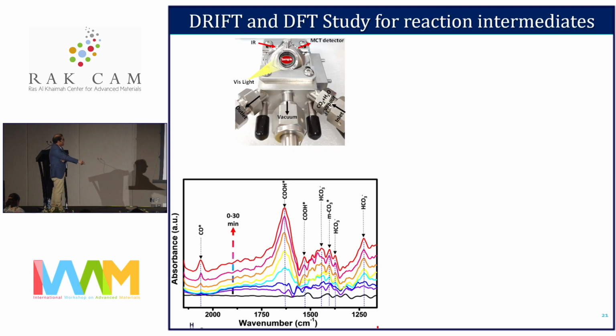To further understand this, we performed an operando study - this is the DRIFT study. After 30 minutes of irradiation, first you have the background without CO2, only the catalyst. Then, with the presence of CO2, you irradiate the light - this is the Mantis chamber. Over time, you first get the carbonate, bicarbonate, and monodentate carbonate. Then you get the COOH*, which is the intermediate state in the 2-electron reduction process. This increases with time, and you get the CO at 2080.